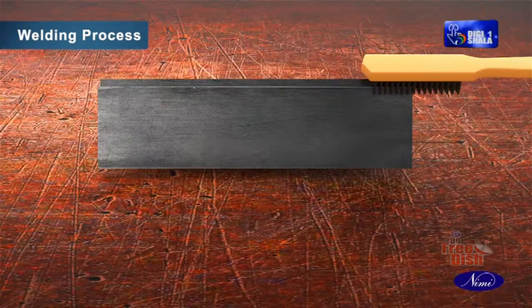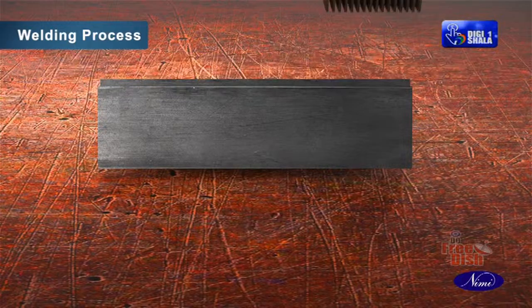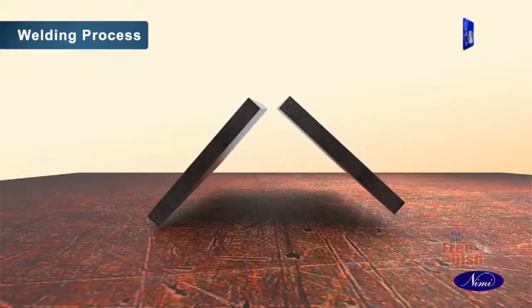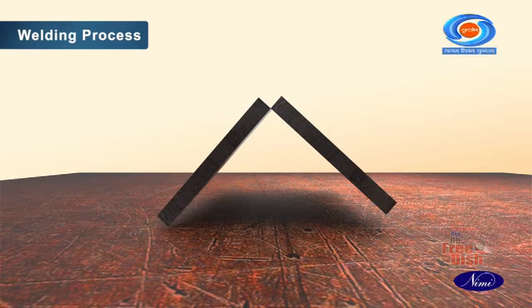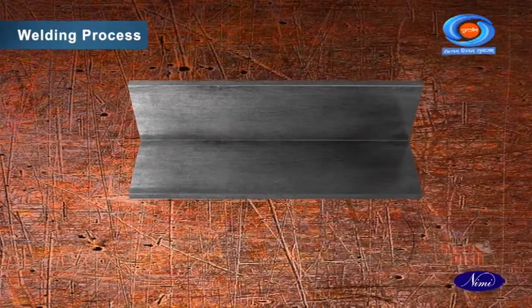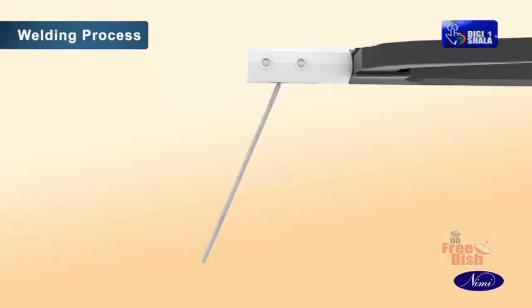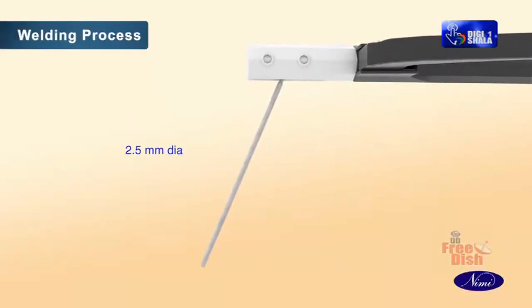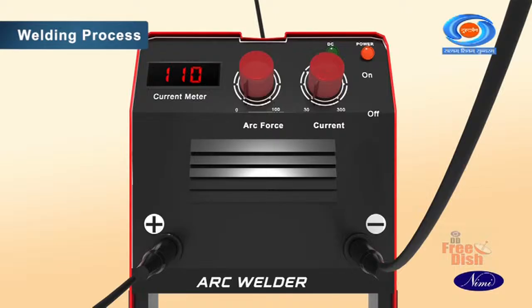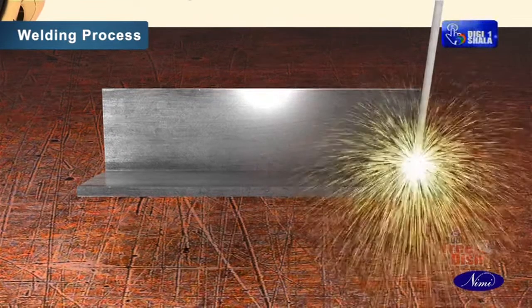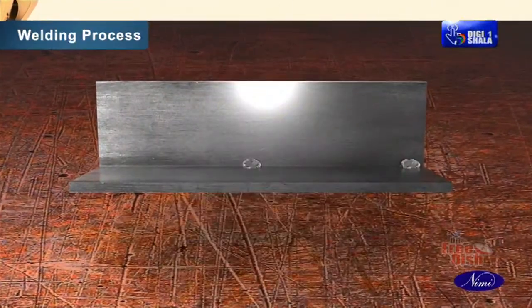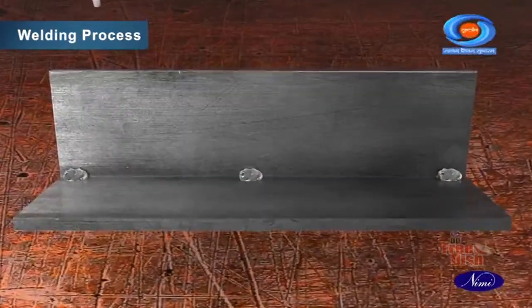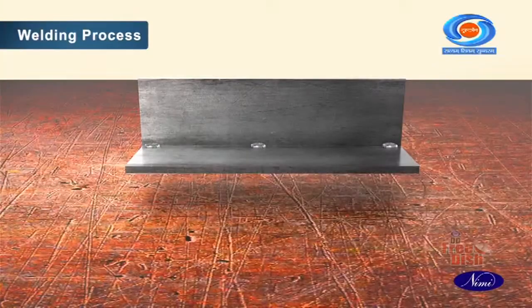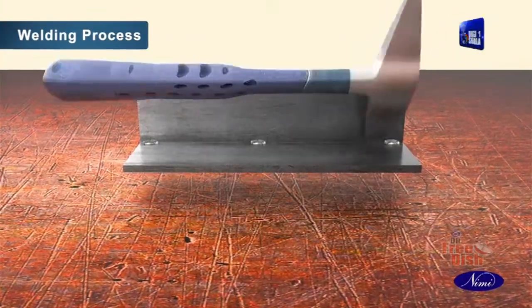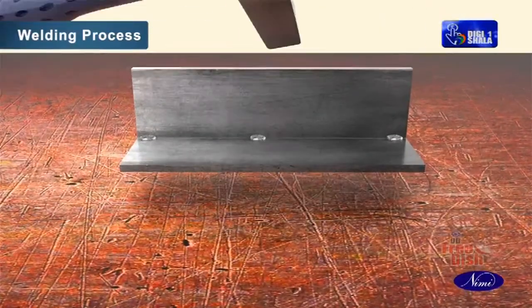Clean the tacks. Check alignment and reset the joint if required. Tack weld the corner joint from inside using a MS electrode 2.5 mm dia and 100 to 110 amps current range. Tack weld with maximum tack length of 20 mm each. Deslag and clean the tacks using chipping hammer and wire brush.